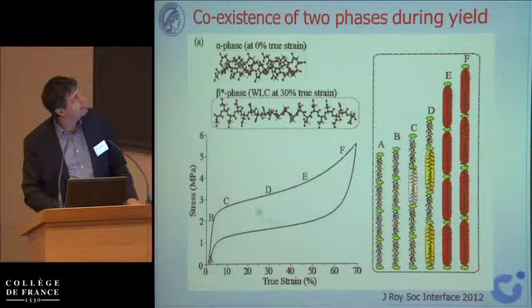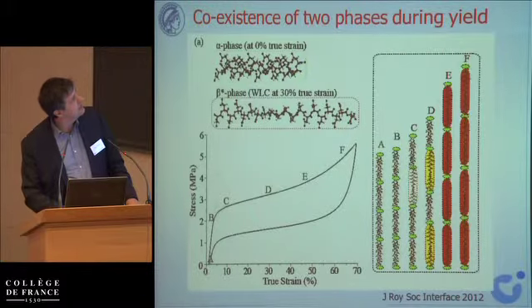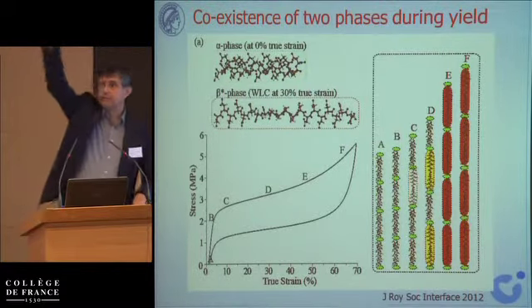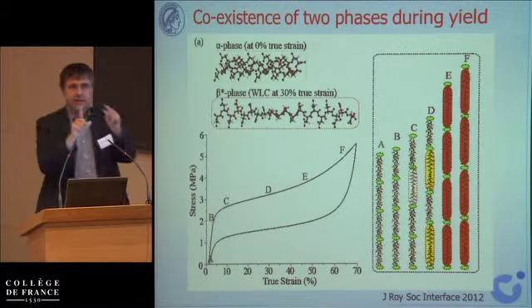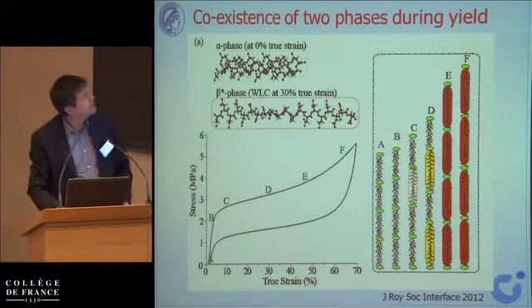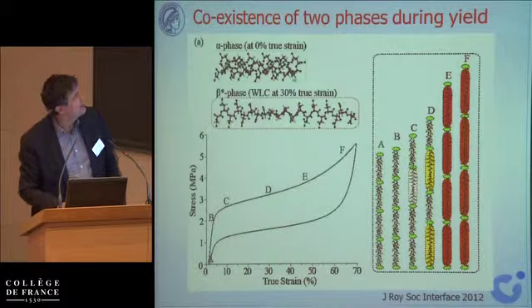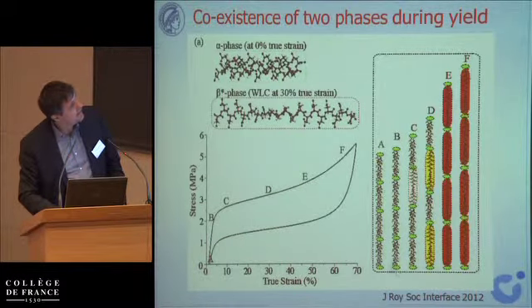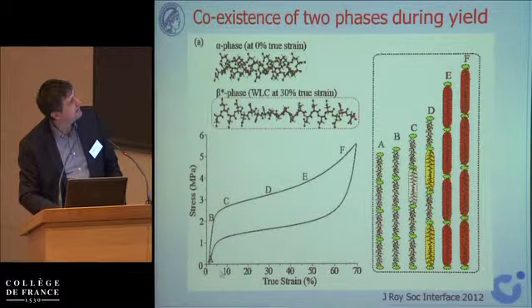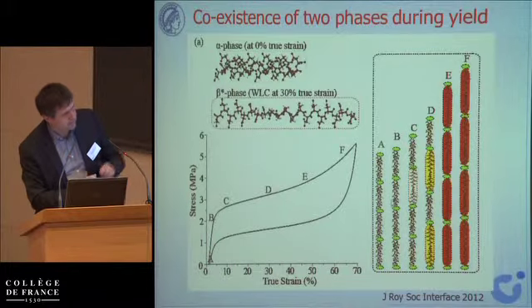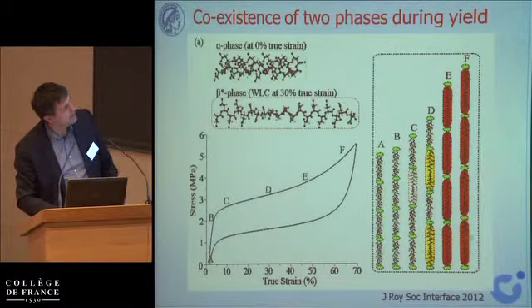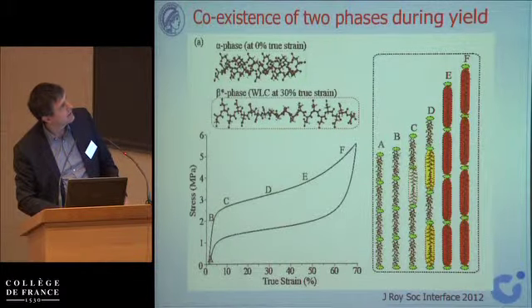And basically here is what's going on. This protein at very small strains is in an alpha helical conformation. And an alpha helix is a conformation where hydrogen bonds hold the alpha helix together in multiple places. So there are many hydrogen bonds that hold this helix together. And in fact, there are many segments of these molecules in a row. So here's an alpha helix, the next. So everything's alpha helical here in the beginning. When we reach the point B, you see that, well, this was rather stiff. So all these alpha helices have just extended a bit. So all the hydrogen bonds are still holding, but you have stretched many of those. So there's a little stretch, and of course the strain that's associated with this is very tiny until we reach